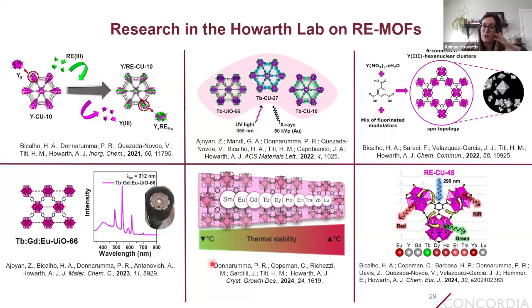We've also shown that you can grow single crystals of all of these MOFs and determine their structure using single crystal X-ray diffraction. In this particular example, we collected the single crystal X-ray data for all of these analogs and analyzed it and correlated it to certain properties like thermal stability of the materials. And we're also constantly interested in studying the photophysical properties of these MOFs.